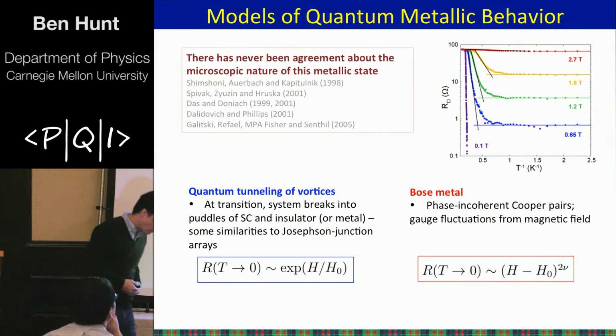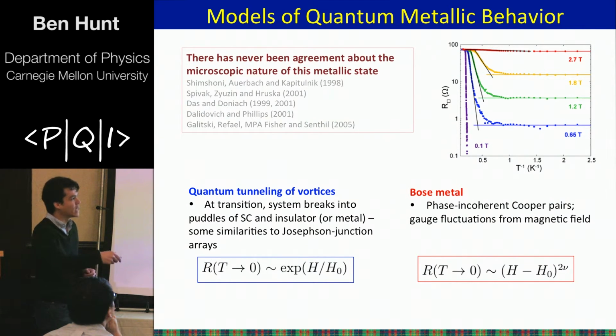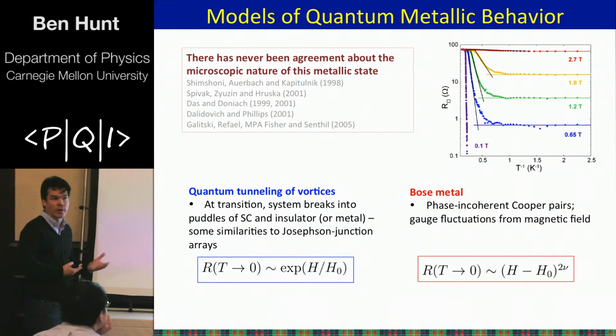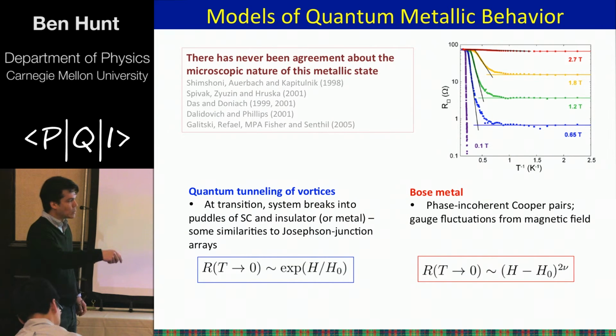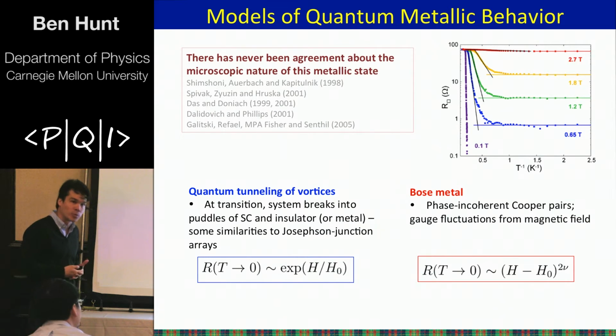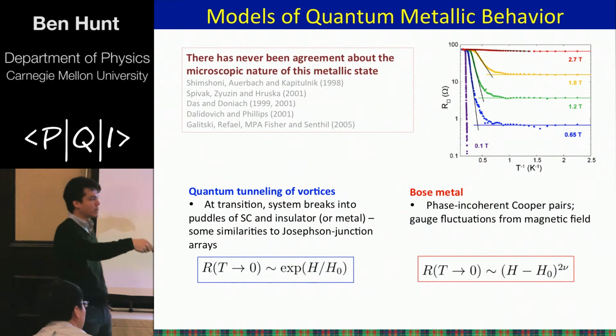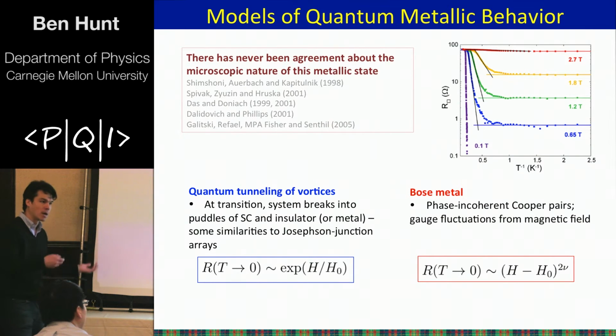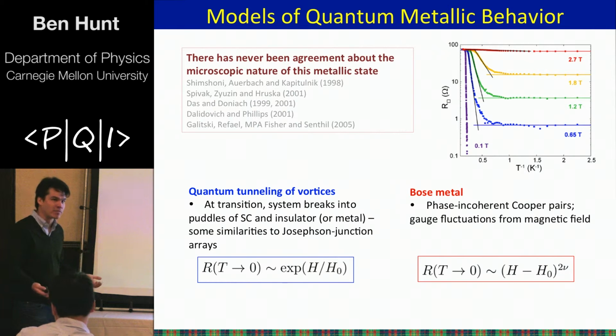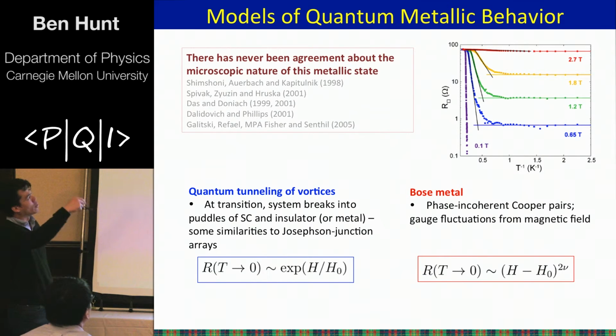Maybe a more radical theory, I don't know how else to characterize it, is the idea that the superconductors become completely phase incoherent, and that you have a bath of Cooper pairs that have lost their phase coherence but are essentially still paired. This idea of a Bose metal, basically a bath of free bosons, has been around for a long time. I should note that our data actually do seem to agree with the predictions of that theory, which are that the resistance at low temperature should scale as a power law and not exponentially. So I would not say that we have completely observed the Bose metal in this case. Our data seem to point towards this idea. But certainly there are new challenges for experiment.